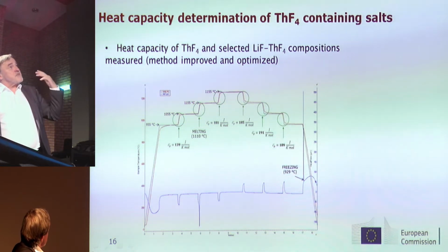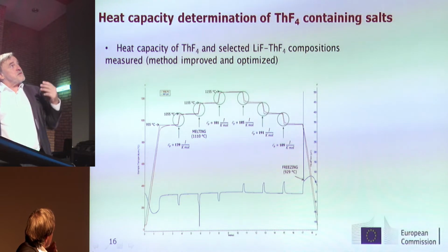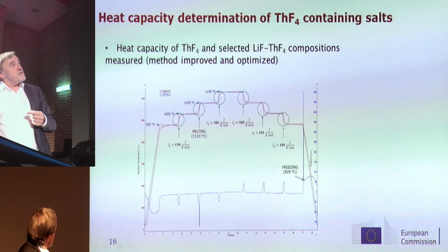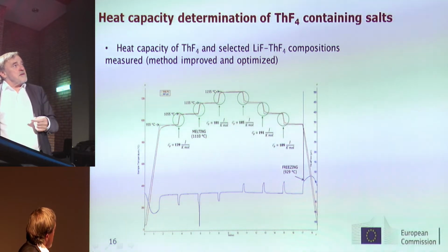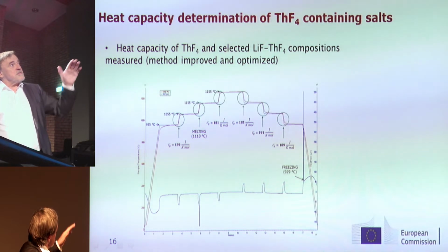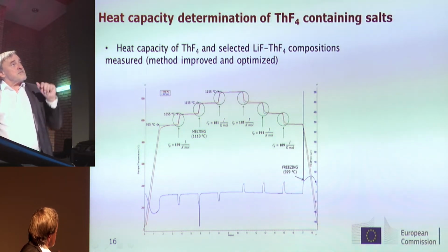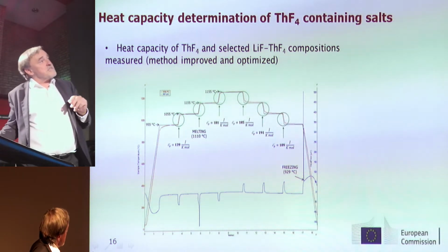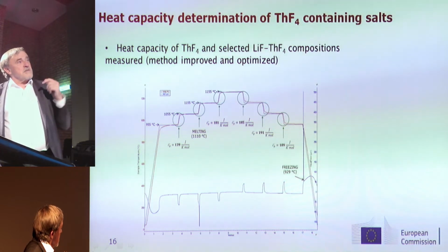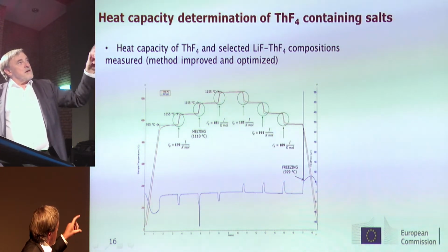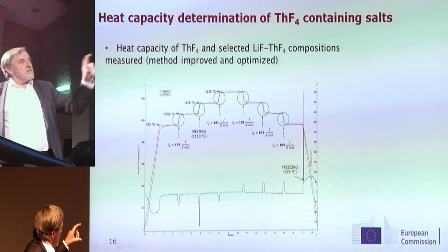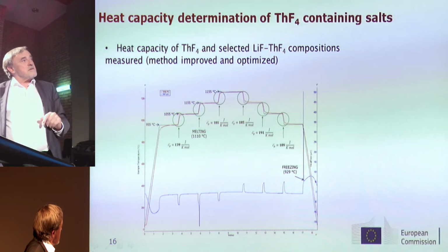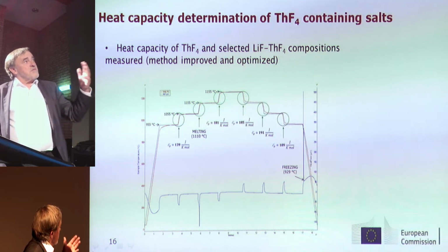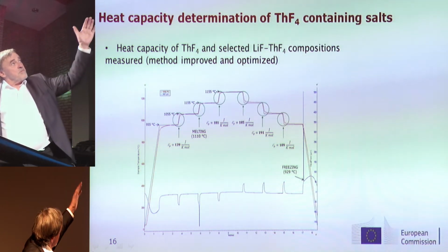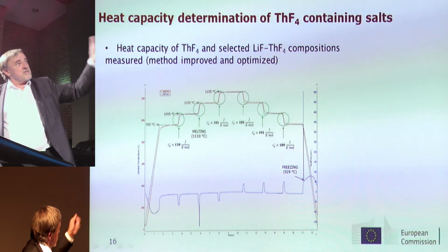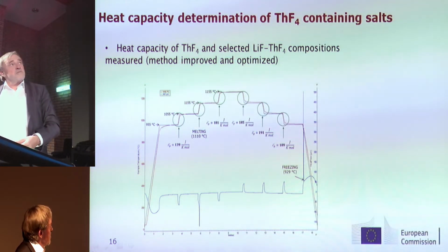Then we have also tried to revisit the heat capacity determination of thorium fluoride and also different mixtures of lithium and thorium fluoride. We have tried to improve and optimize this method, where we have applied a temperature program, as you can see, a steep increase in the beginning, but then essentially stepwise increase of temperature up to 1155 degrees Celsius, and then again the decrease, and registered the heat flux, which has been measured in the blue curve, and then making the ratio between the temperature increase and the signal that is registered in this heat flux curve. We can calculate the heat capacity at these different points, at different temperatures, and this is something that we have tried to refine, as I said, both for the thorium fluoride pure, as it is shown here on the view graph, but also for different mixtures, lithium fluoride and thorium fluoride.